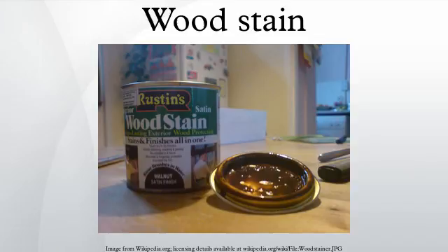New lumber, such as pine, can have wax-like sealants put on at the mill that will prevent proper staining. Stripping or sanding the surface may be required. White stains composed of metal oxides, namely titanium dioxide and zinc oxide, do not penetrate well and remain on the surface. In such cases, wear easily reveals unstained wood. They are also fairly opaque.